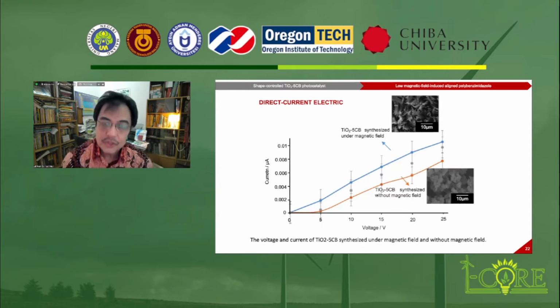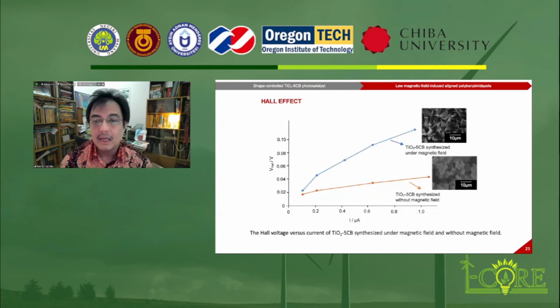The Hall effect also shows the same thing. The titanium dioxide 5CB sample synthesized under a magnetic field, here the blue one, gives a higher Hall effect when compared to the one without a magnetic field. This is the orange one.